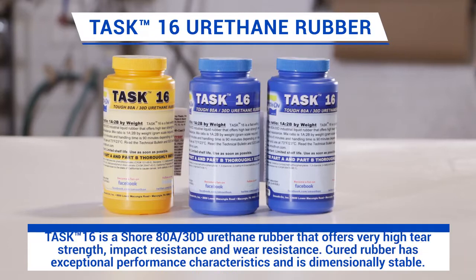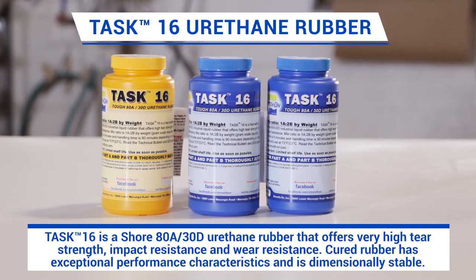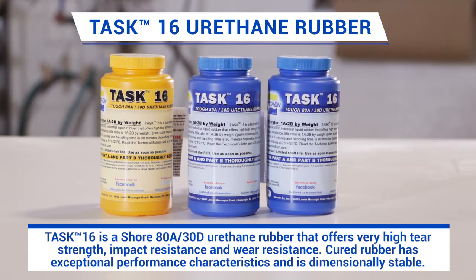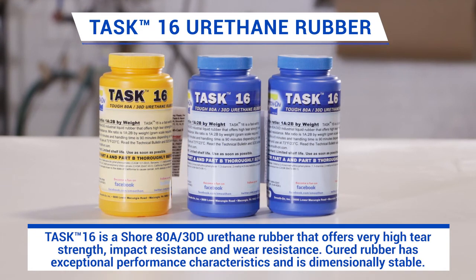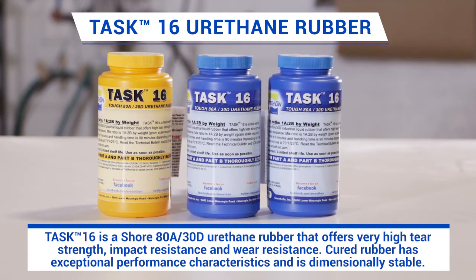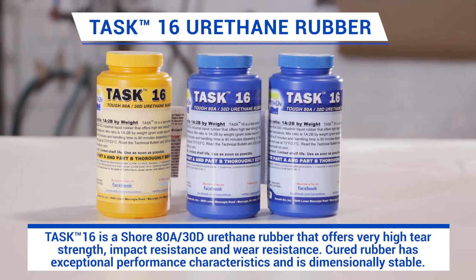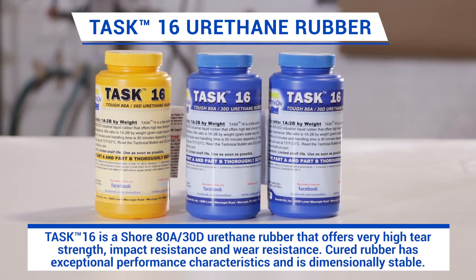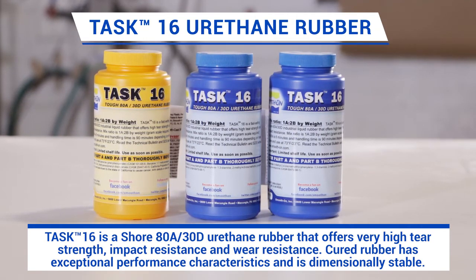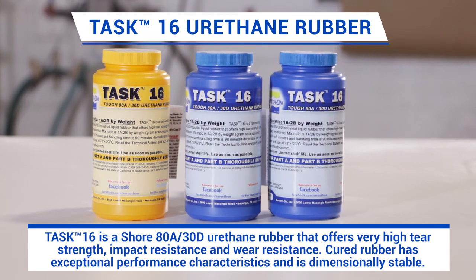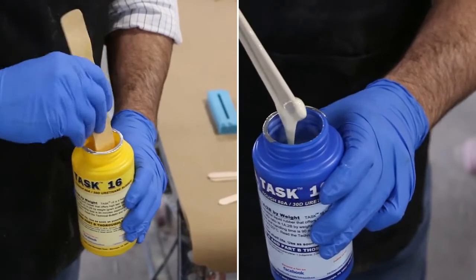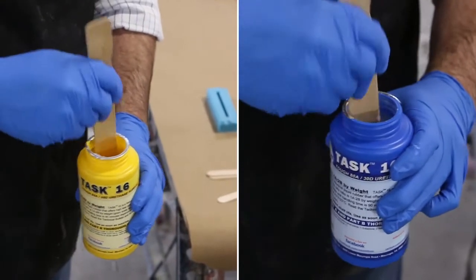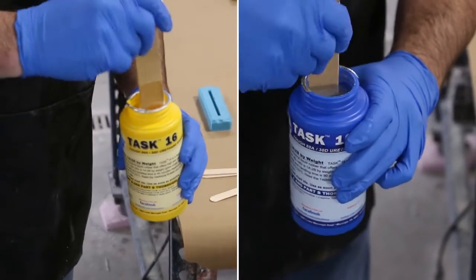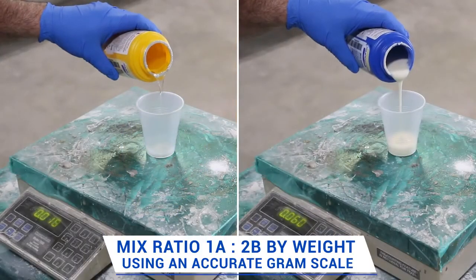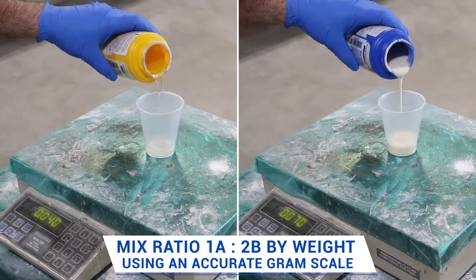I chose Task 16, a fast-setting urethane rubber. The Task 16 is rigid enough to hold its shape, but still flexible enough to contour to the curvature of the sink mold. This will also be forgiving during demold by not chipping the concrete like a rigid material most surely can. Begin by premixing both components and dispense at a rate of 1 part A to 2 parts B by weight using an accurate gram scale.